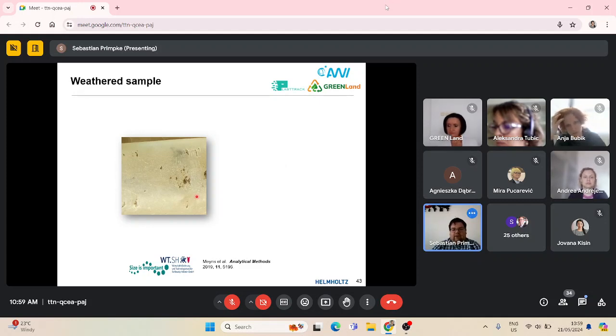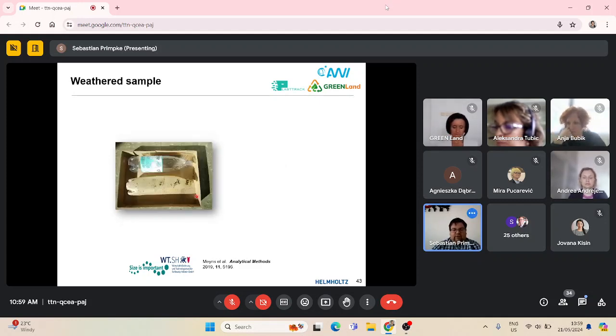I found this flask on the beach of Helgoland, and luckily I just recognized that I had the same one currently in the office. We had one of these flasks with the cap on it, so we wanted to identify both. We then moved our system onto it, and you see here the contour level, and then we try to measure the surface area.